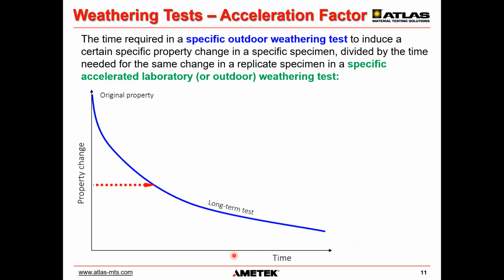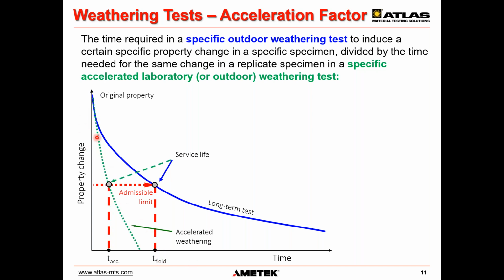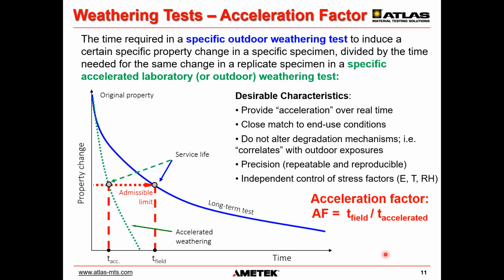All right, so what is an acceleration factor then? In general, we have the blue curve here, which is a property change over time. The x-axis is time. After a certain time in the field, the pass-fail criterion is met. This is characterized by this red line, and this is then called service life. If we have a faster test, which doesn't distort the mechanisms, we reach that service life after a shorter time because it's a faster test, it's an accelerated test. And these two times divided by each other is the acceleration factor. It's as easy as that. It's very, very simple. The definition is very simple, but what's behind it is very complex.